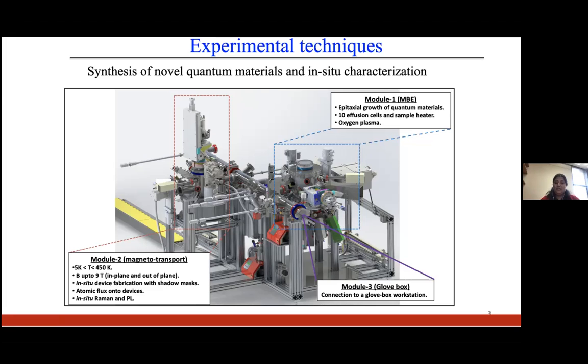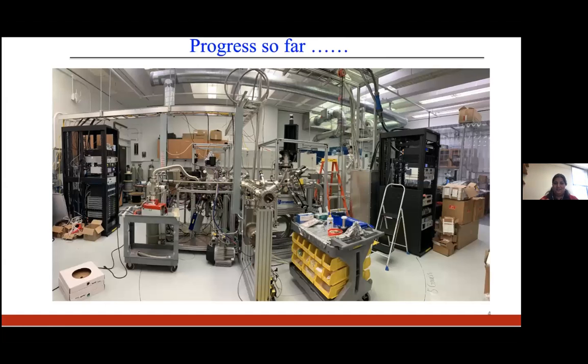We can do the in-situ device fabrication using shadow mask and sputtering. And we can also put atoms like alkali metals or hydrogen atoms onto our devices. And we can also do in-situ Raman and photoluminescence measurement. So it's a unique experimental setup that we are setting up here at Carnegie Mellon. And this is my vision.